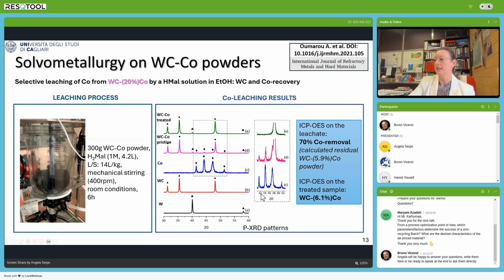And ICP analysis on the solid material and on the solution agreed, finding 70% of cobalt in the leachate, and so around 6.1% of cobalt in the remaining tungsten carbide cobalt mixture. So, by making this selective leaching, we obtain the right composition, but we also needed to assess the quality of the material, assessing the possible oxidation